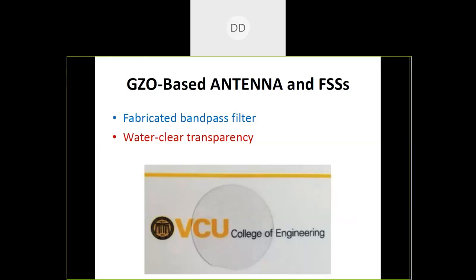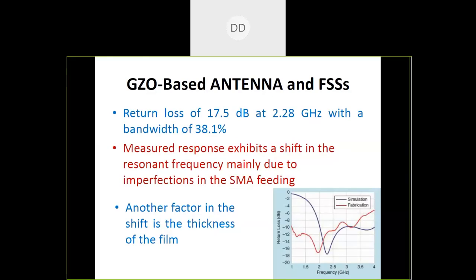Then the fabricated antenna and the filters were measured, and the characteristics were measured using the VNA. The researchers reported that they observed a similar pattern, but there was a small shift in the result.